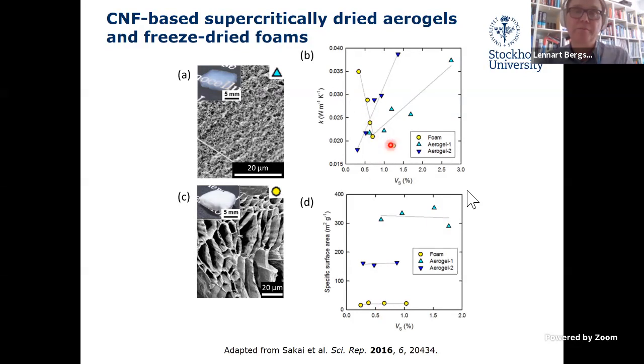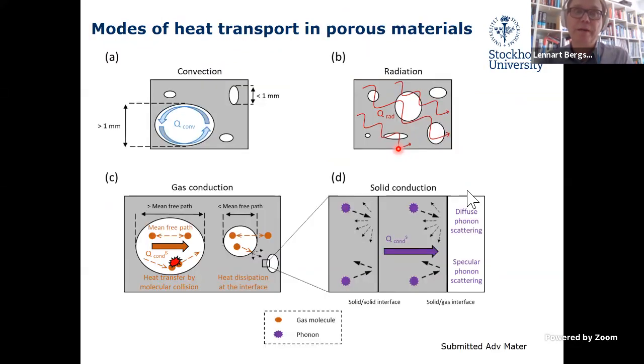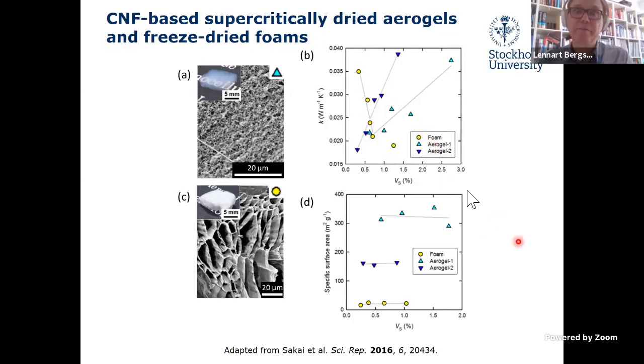That suggests that even though you reduce the gas conduction for the supercritically dried foams, aerogels, it is the reduction of the solid conduction in the freeze-dried foams which plays a bigger part and can explain this behavior.